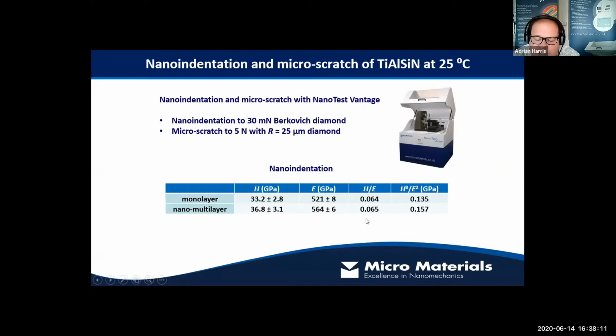Now, these predictions don't always work perfectly, because sometimes it's not the hardness and the elastic modulus that defines a coating's performance. So measuring those things and trying to use them as a predictor is not always reliable. But it's useful to then perform the complementary tests, the scratch tests and the impact tests, to work out whether or not these predictors are precise. If they're not precise, then there's something else going on with the coating we need to know about. So it could be an adhesion-related failure.